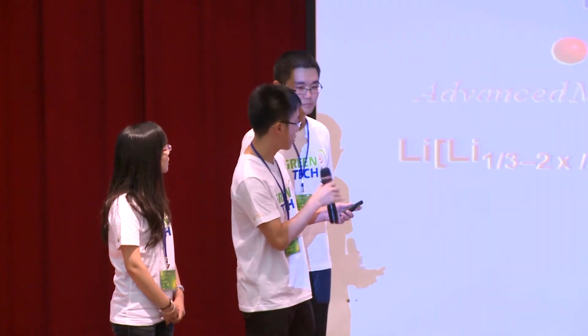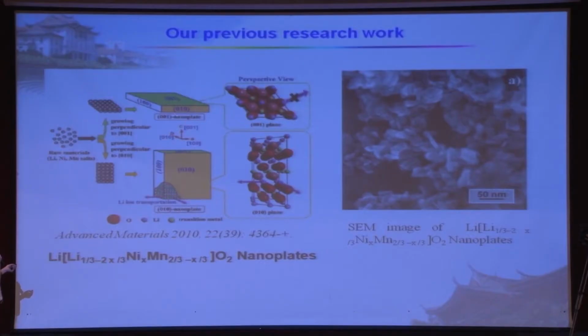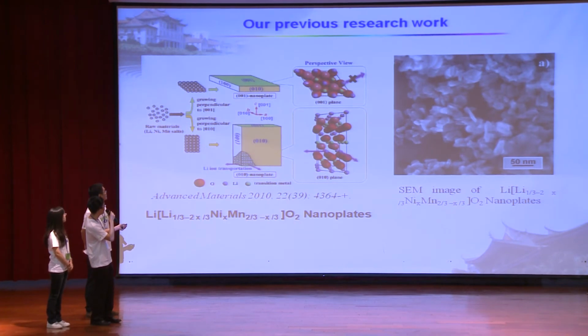Normally, when you have multiple components in your system, manufacturability is a problem. How do you make these 4 elements according to what you design? Are there adjacent phases which can deteriorate your performance? So you see, this is the structure of the layered cathode material. When we analyze the crystal structure, we can see the O1 plane is close packed, so it's not good for diffusion of lithium ions.